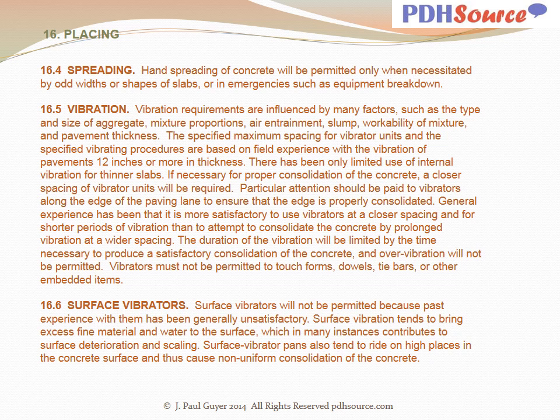If necessary for proper consolidation of the concrete, a closer spacing of vibrator units will be required. Particular attention should be paid to vibrators along the edge of the paving lane to assure that the edge is properly consolidated. General experience has been that it is more satisfactory to use vibrators at a closer spacing and for shorter periods of vibration than to attempt to consolidate the concrete by prolonged vibration at a wider spacing.